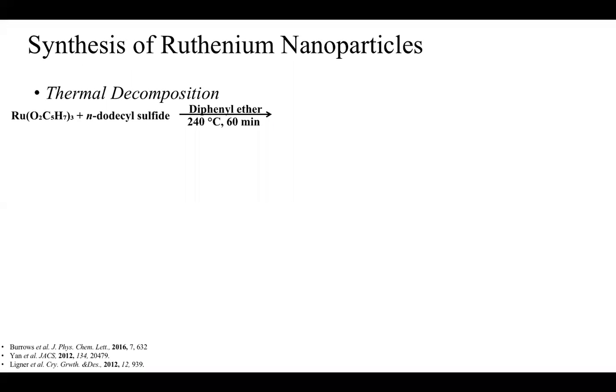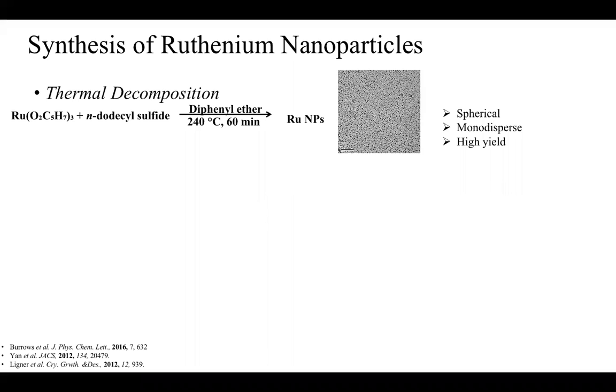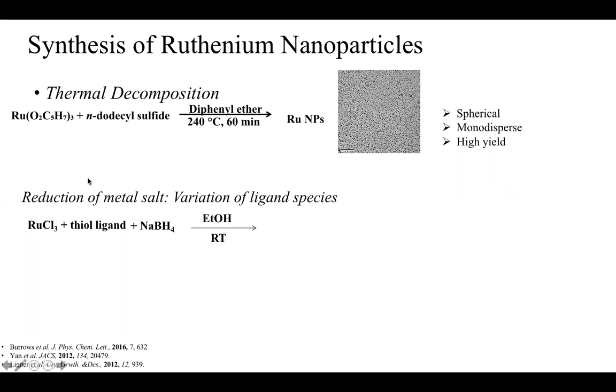Another study we looked at, or synthesis route we looked at, was for ruthenium nanoparticles using thermal decomposition. So by using a ruthenium precursor in the presence of n-dodecyl sulfide and a diphenyl ether solvent, so it can be done at higher temperatures over time, we were able to kind of break down and produce ruthenium nanoparticles that were spherical and monodisperse in high yield. So as you can see from the TEM image, again, we were able to make these particles, and our support of that was through our TEM. But again, because of those high temperatures, we wanted to find a way of trying to build shapes without having to use such extreme methods.